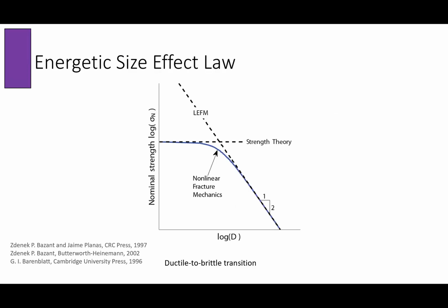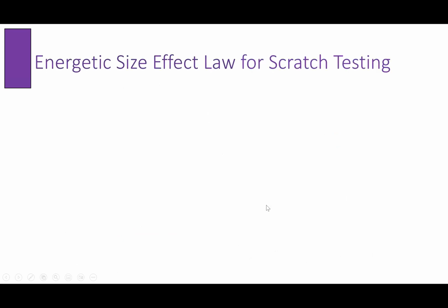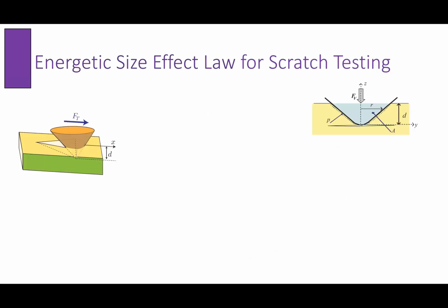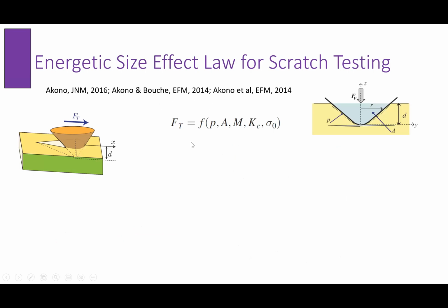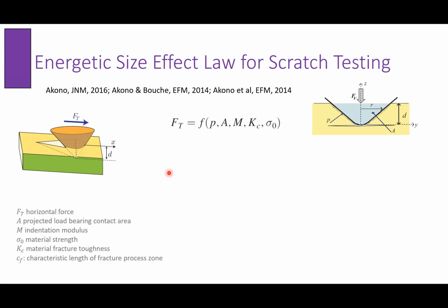So one way that we actually extended it after my PhD was to see how we can extend this LEFM model to take into account nonlinear fracture mechanics. So when you have nonlinear fracture behavior with a mix of both ductile and brittle phenomena taking place, that's actually using, in this case, the energetic size effect law. For the energetic size effect law, again, the different step is really using dimensional analysis, and then we start from the LEFM solution.